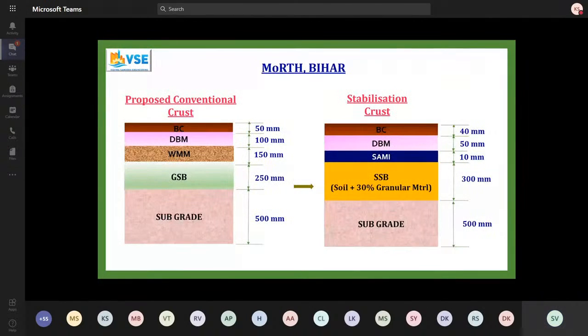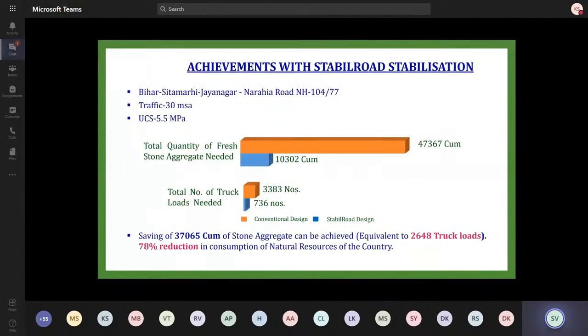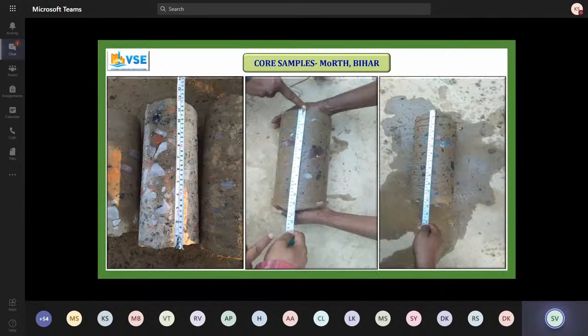If you see here, GSB, and so we've gone for 300 mm of stabilization followed by SAMI. Oh, I'm sorry, I think we did use DBM. It's a national highway. I think it was 30 MSA. So we used a DBM of 50 and then BC of 40. Here again, 78% reduction, but the aggregate you see, the usage is mainly for BC and DBM. The actual stabilization part, there's hardly any aggregates that we used. These are the cores in Bihar.